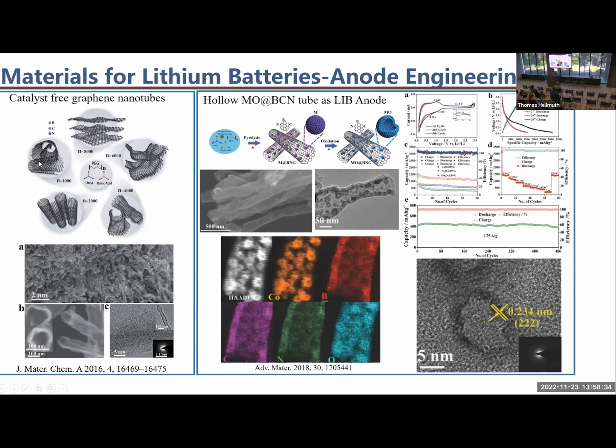So we tried to fabricate the graphene tubes. Now, these are different from carbon nanotubes. You might be familiar with carbon nanotubes, but these are different, as you can see here. We wanted to increase the internal diameter of the tube and then load the transition metal species inside the tube so they can be protected from the electrolyte and they can still provide the charge and discharge. So you can see here, these particles were then loaded onto this large diameter tube.